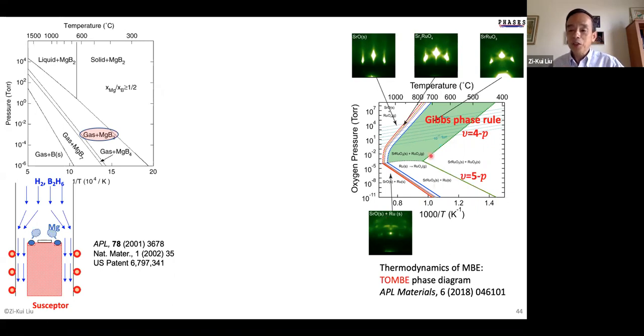Actually you have 2 very different conditions here. This is like a closed system, this is like an open system. So this diagram combines the closed system and open system together, 2 diagrams actually, 2 different conditions. Why does that happen? Because of the MBE process, if you increase the oxygen partial pressure high enough, you don't form this ruthenium solid anymore, it's completely oxidized. So you change the condition completely.